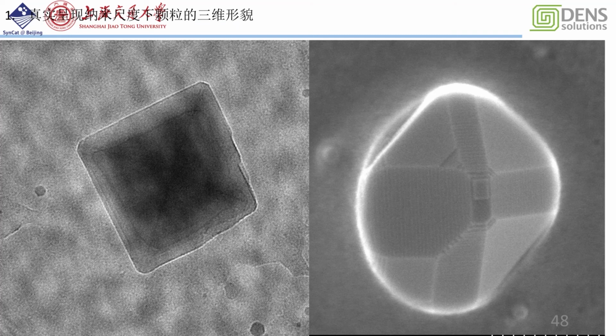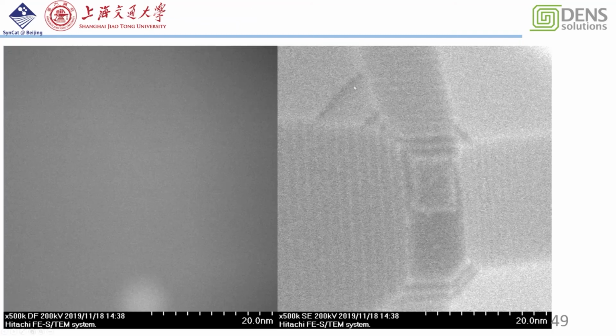When we increase the magnification even higher, we can see the steps on the surface, and the thickness of the step is about 2 nanometers, which is in good agreement with our assumption during the calculations. And also from the dark field image, we can clearly see the image of the metallic iron, but from the secondary electron, we cannot see the particle. It confirms this particle is in the bulk.